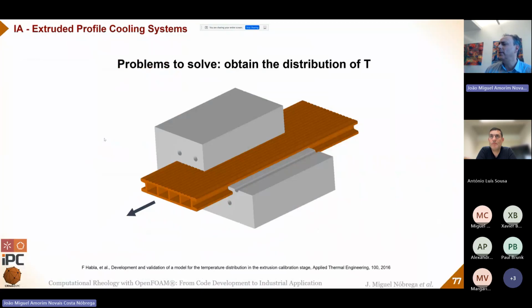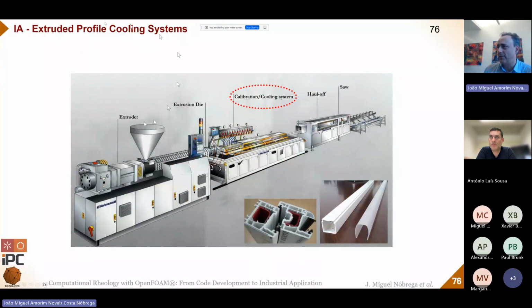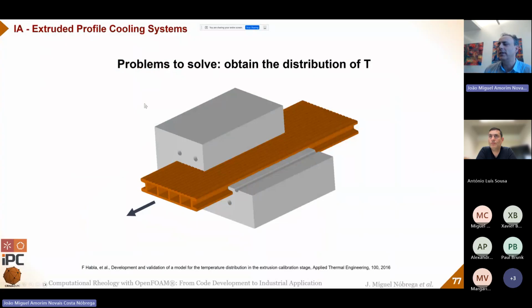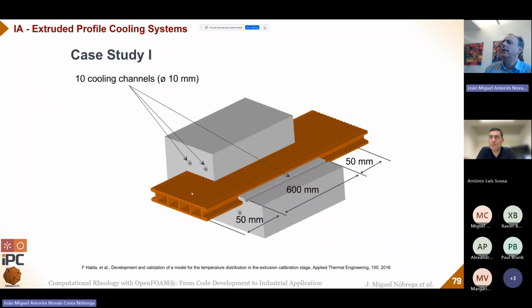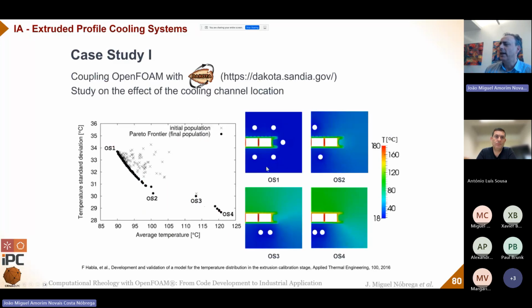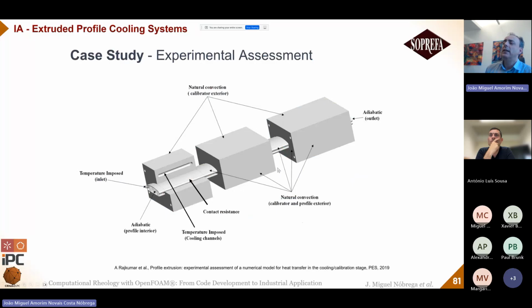We also have been using it to model the second part of the extrusion system, the calibration, in this case cooling, so a metallic part, a profile that is cooled down, and the main unknown here is where to place the cooling channels. And we showed, again by coupling it with Dakota, that the optimization framework is able to identify good solutions.